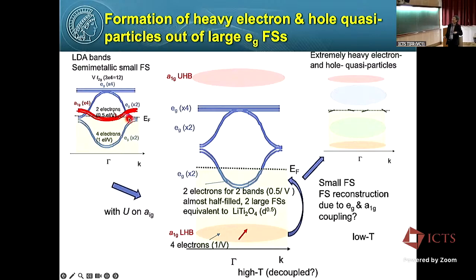Maybe let me consider the effect of correlation onto the LDA band. If I put in correlation virtually, pretending as if I'm a theorist, then this is going to split the narrow A1G band into a lower Hubbard and an upper Hubbard band. And of course, this lower Hubbard band contains 1 electron per vanadium. That is 4 electrons. So we have 4 here. And the remaining 2 go to the lower Eg prime band. Okay. And since this band is doubly degenerate, we have a half-filled Fermi surface for Eg.